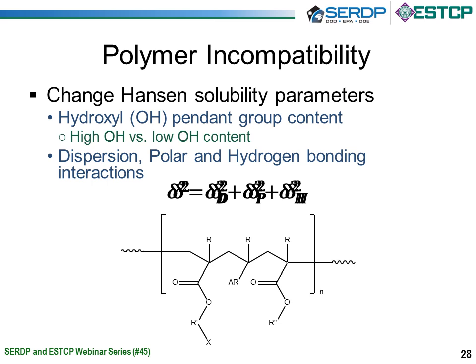A very generic structure of the acrylate that we utilized in preparing the polyols from Estron is shown down below, where R prime and R double prime are aliphatic contents, and the X represents the hydroxide, or in some cases some other heteroatom such as a halogen if we choose to incorporate it. In short, we wanted to ensure that the high and low OH polyols were compatible enough to react, but at the same time we wanted to achieve the phase separation that would form this surface texture or roughness.